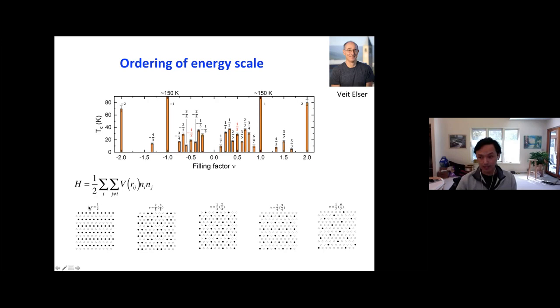For instance, 1/2, 2/5, 1/3, 1/4, and things like that. These are the expected charge patterns that we would get for these fractional states here. And we can also measure the melting temperature of this charge order state. And this melting temperature agrees very well with just a simple extended Hubbard model in the flat band limit.